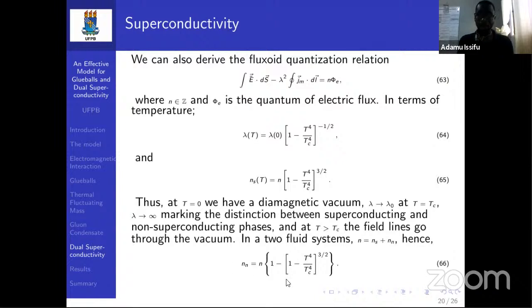Now let's focus on this equation 66. You realize that as the temperature increases and the superconducting monopoles are decreasing, the normal monopoles will keep increasing. So at a critical temperature, where the superconducting monopole density vanishes, that is where you have the normal monopoles being at their maximum. They normally call this the two-fluid system. It is based on a superconducting material where they found that there was a normal current and a superconducting current that led to this analysis.